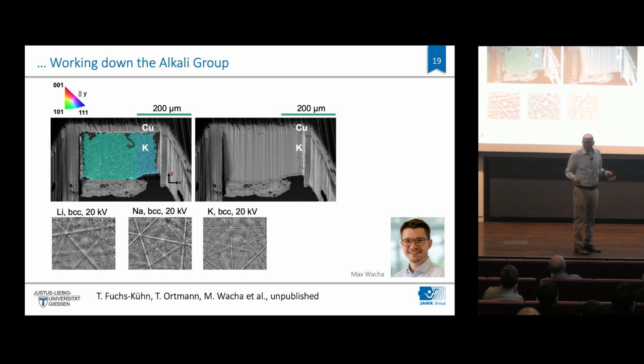Okay, now I'm a chemist, and it's very important, of course, to go down the row in the periodic table. We even managed, meanwhile, to look into potassium. I have a very brave PhD student, Max, who managed to grow potassium on potassium beta alumina. There you will have, with 1 milliamp per square centimeter charge, 20 micron thickness, and you get very nice Kikuchi pattern. The electron density is higher, so everything works reasonably well, and you get almost only 1 grain. So it's even single crystalline growth of potassium, because it's even faster. Diffusivity is extremely fast within potassium.